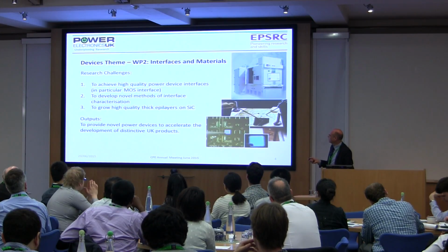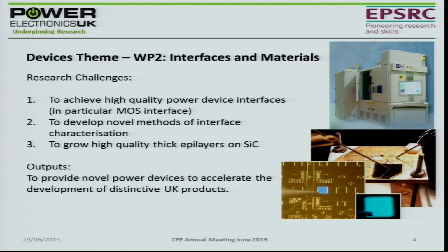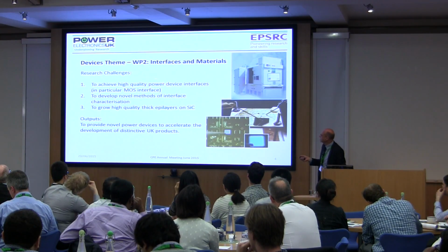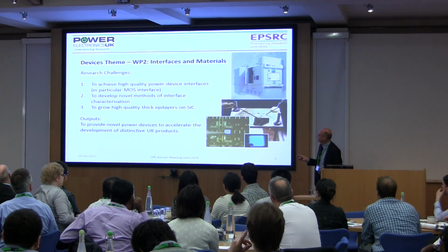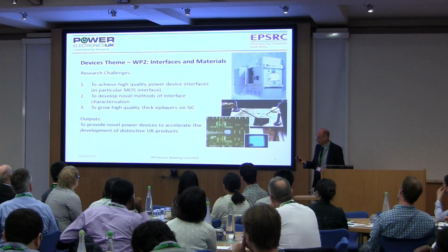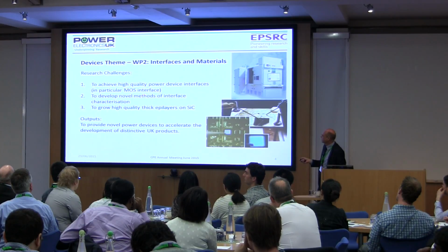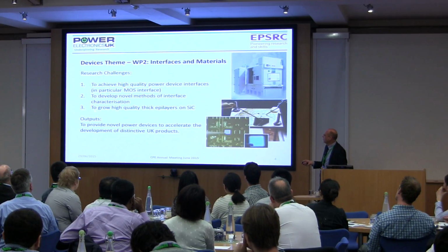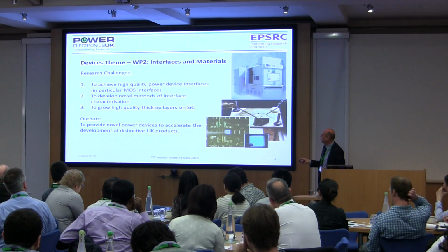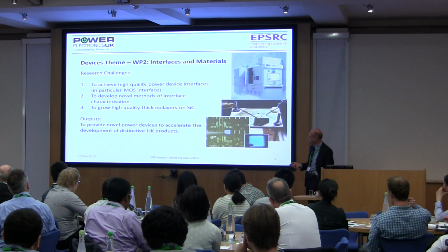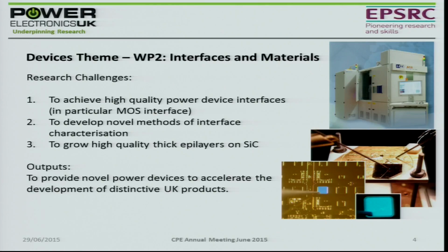The second work package is on interfaces and materials. So in any semiconductor device, there's lots of different interfaces between different materials, between silicon and silicon dioxide, between different semiconductors, different insulators, and this really is looking at those properties. In particular, we're looking at improving the quality of MOS interfaces for silicon carbide devices. Big issue. We're looking at methods to characterize the interface. And the final part of this work is looking at the growth of high quality, thick epitaxial layers of silicon carbide. Thick being the operative word there for high voltage devices. So we're looking at layers bigger than 30 microns.